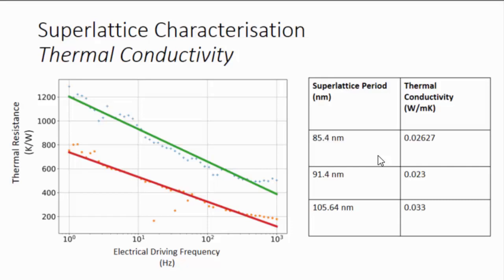These numbers, for those not familiar with thermal conductivity ranges, are a reduction of about 1 or 2 orders of magnitude, depending on what you compare it to the bulk, which is really quite large, especially for a room temperature measurement.